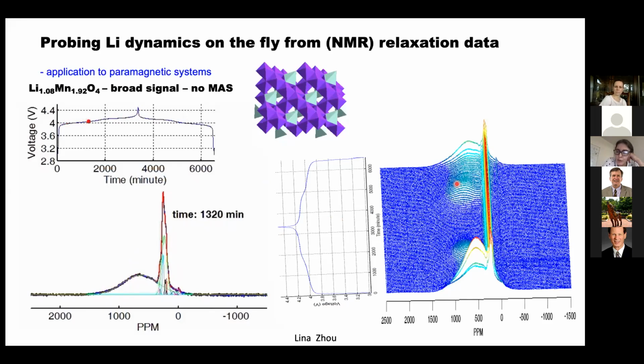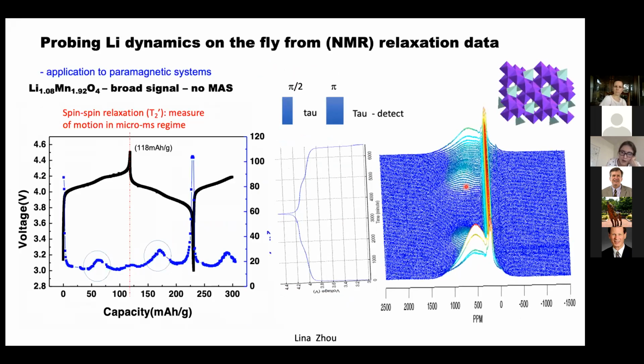If you do your experiment properly, your signal should be proportional to how much is there. So there has to be something else going on. And that, of course, is how you do the measurement. The way we do the measurement, without going into gory NMR details, is a so-called spin echo experiment, where you apply a pulse, you wait a time, you apply another pulse, and you detect. The point of this second pulse is to refocus the signals.